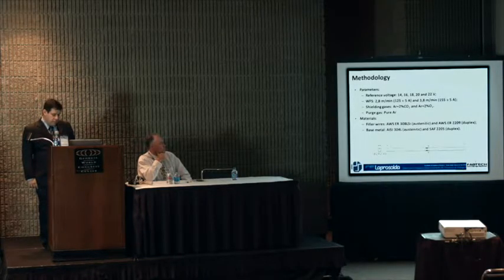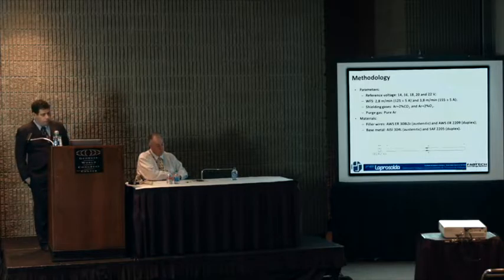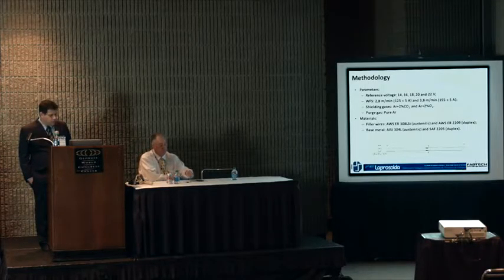Shielding gases, most used for, let's say, those two wires: argon with 2% of CO2 and argon with 2% of oxygen. And for purging, we use pure argon. The filler metals were the standard ones, 308LSi and 2209. The base metals we use most were the 304 and the 2205 for duplex.